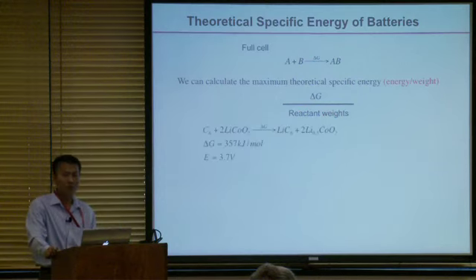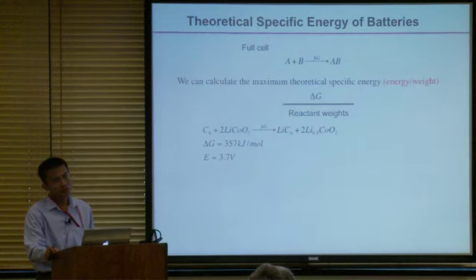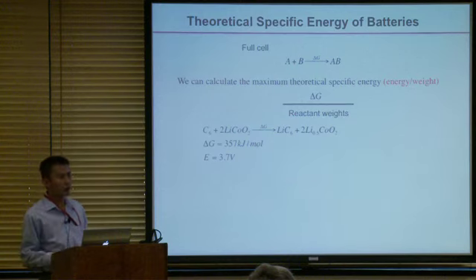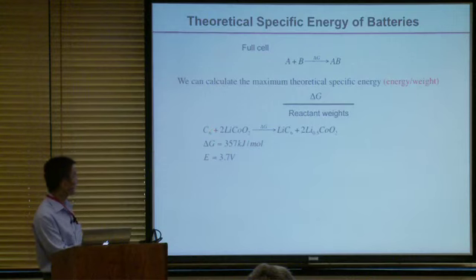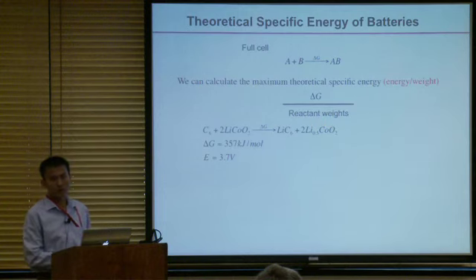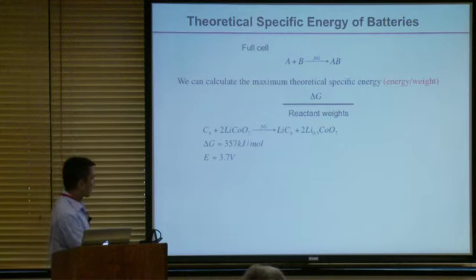Now let's do a really simple estimation on the lithium ion battery used in the current technology. Some of you might not know, when people talk about this parameter, what exactly they mean. This is the reaction, carbon as a negative electrode. It's graphite carbon. We use C6 right here, 6 atoms, to indicate that. You have lithium cobalt oxide. Now you put lithium into carbon, you charge your battery, produce lithium carbide, and lithium cobalt oxide now goes from 1 to 0.5 lithium right here. Usually people don't go down more. If you go down more, lithium cobalt oxide is not stable. So this will be the limit.